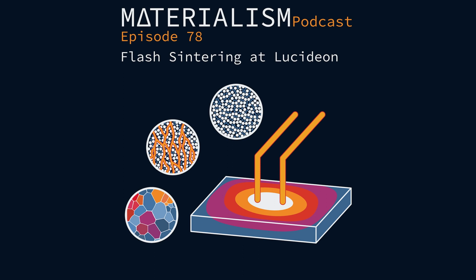So in its simplest form, in terms of contact flash, we're sandwiching a cylinder of alumina or zirconia between two electrodes. We're heating the furnace up. The electrodes are just resting on the top and the bottom of that ceramic piece. Heating the furnace up to, say, 800, 900 degrees, applying that electric field, and then seeing a rapid sintering process occur with some optical emissions.